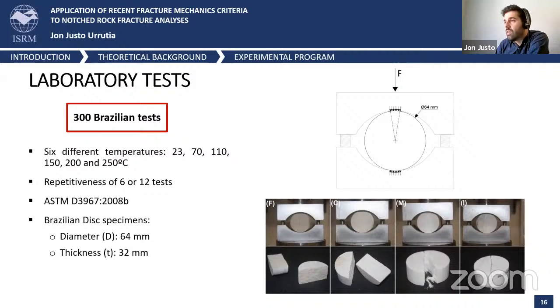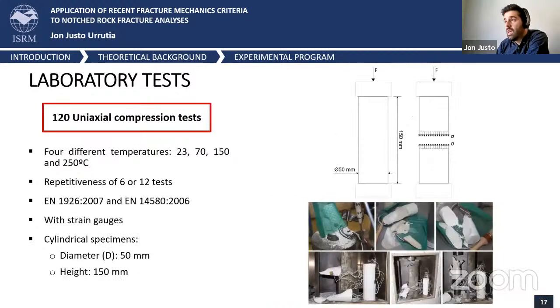In order to define the tensile strength of the rocks, 300 Brazilian tests have also been performed at different temperatures, again from 23 to 250 Celsius degrees. In this case, using disc specimens with 64 millimeter diameter and 32 millimeter thickness. And the same for the uniaxial compression test, again performed at different temperatures up to 250 Celsius degrees. In this case, as we needed the deformational parameters, we had to use special strain gauges to measure both the Young modulus and the Poisson ratio at high temperatures, which was not an easy task. Probably it was the most difficult part of this experimental campaign, because these strain gauges were quite sensitive.